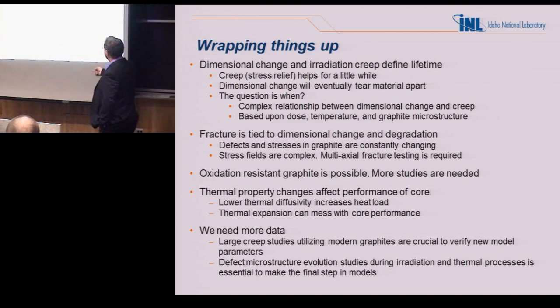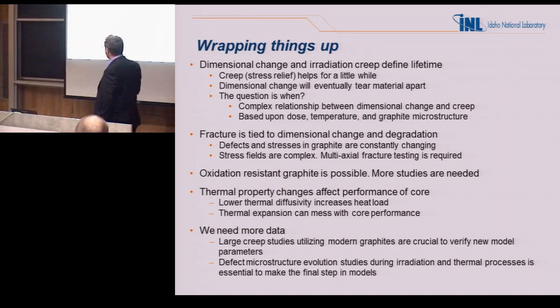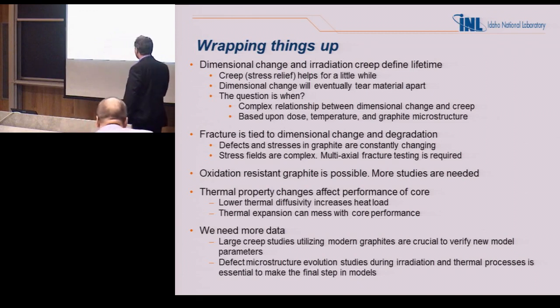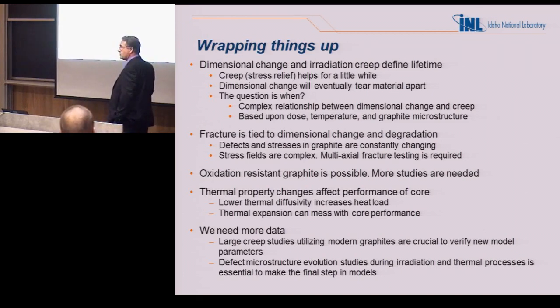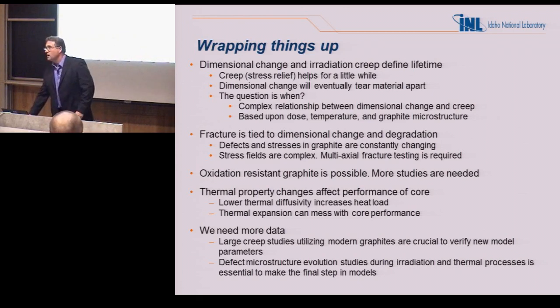So, wrapping things up, dimensional change is the big one. We've got to figure that out and how radiation creep affects it. Fracture, of course, is tied to the dimensional change and any kind of degradation. You can produce an oxidation-resistant graphite. The thermal property changes affect the performance of the core, and we need much more data, and we're getting it. I'm about halfway through my program, and I am putting in my 4th capsule in 2 months. So right now I have 1,500 samples that we're testing at this point.